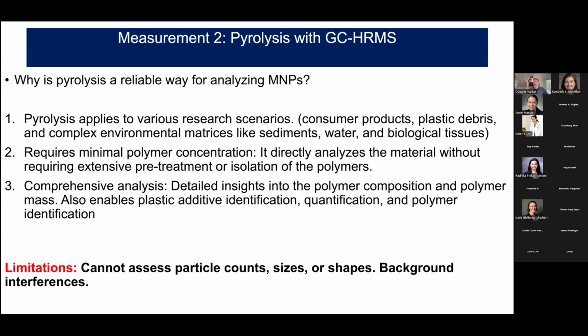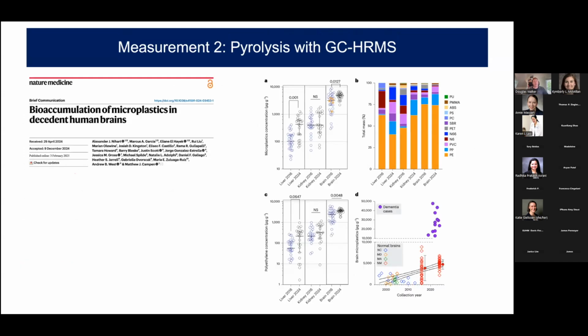However, it's important to recognize there are some limitations of these methods. It does not allow us to assess particle counts or shapes, so it may not be comparable to some of the microscopy methods. But most importantly, there are some organic materials that, when pyrolyzed, can actually break down to the same pyrolytic products as polymers. And if you're not removing those background interferences, you can incorrectly measure those compounds as plastics. And I don't want to be negative about this recent study that came out, and I think it's important to advance the methods, but you can see that effect occurring from the pyrolysis analysis in this recent publication from Nature Medicine.